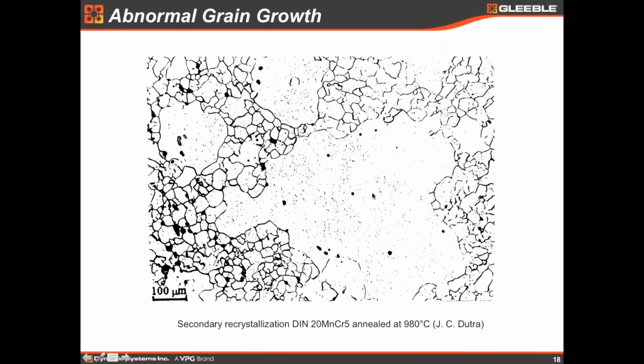So there are three ways that these abnormal grains can be formed, and one is the partial dissolution of precipitates in certain areas. So in certain areas we have the dissolution of precipitates, and then the grain boundaries that were pinned by the precipitates at a certain time get free to move, and then they move faster than the other grains, and they grow faster, absorbing the normal or small grains. So this is basically the most common way to generate abnormal grain growth and form these big grains in the microstructure.